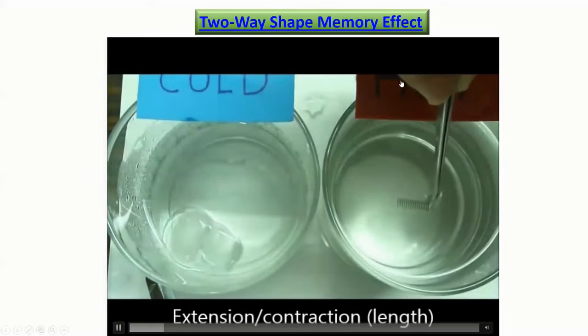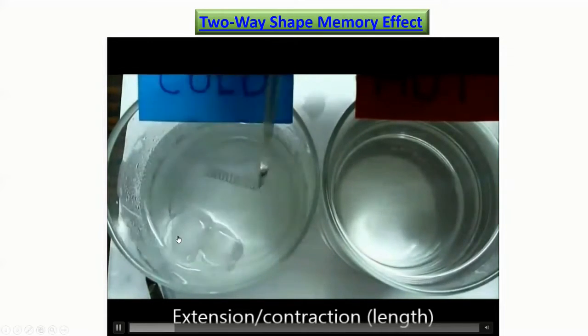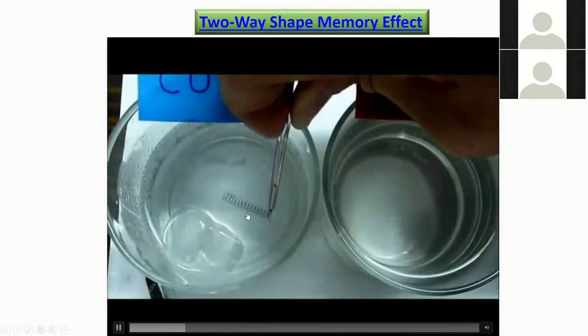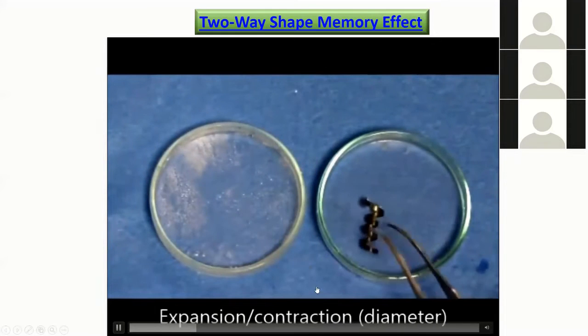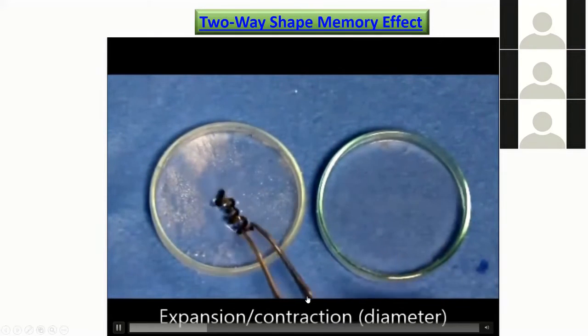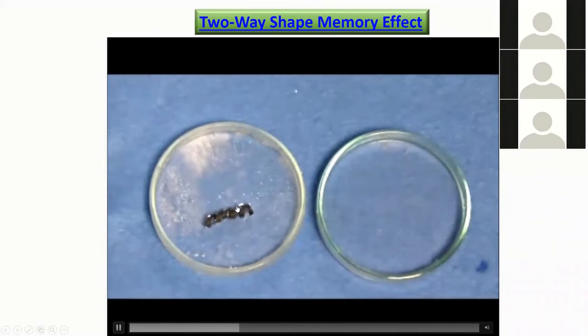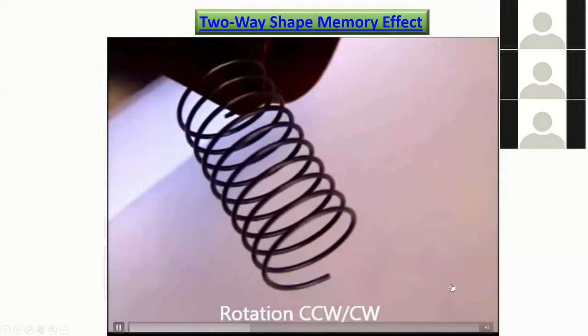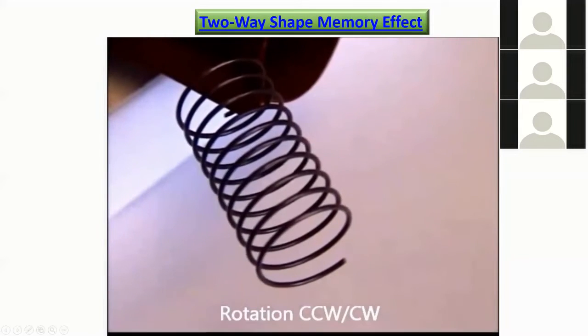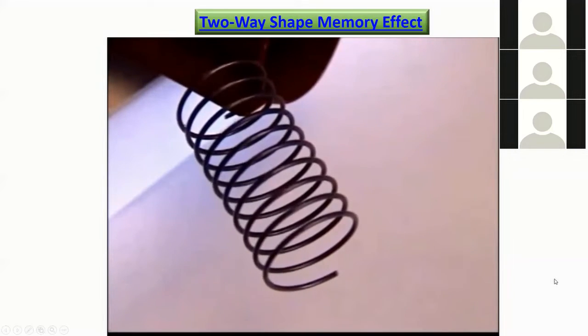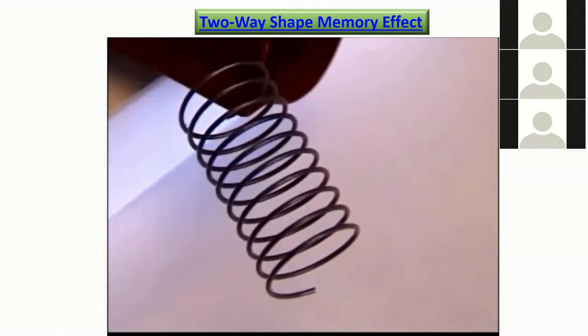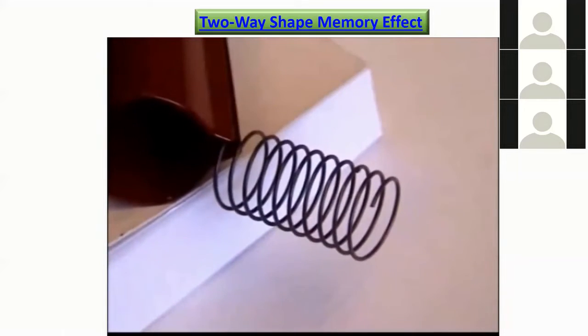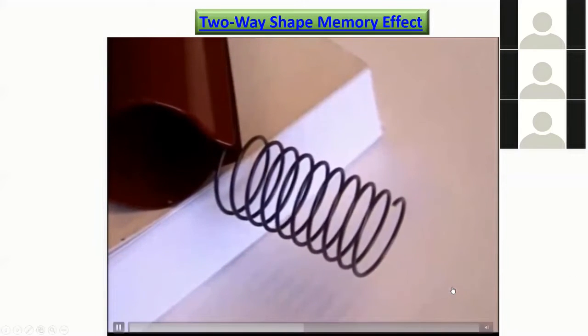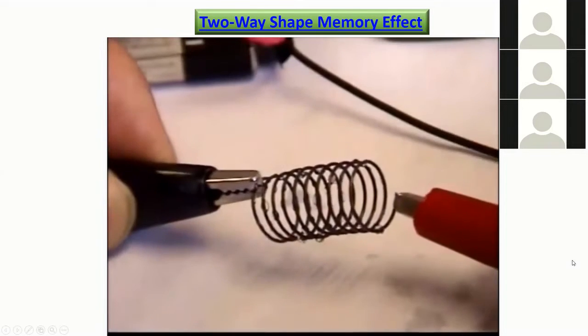So you can see that this is a hot water or hot liquid, and this is a cold liquid, and the spring can have two different shapes. Okay, with the change in the diameter, you can see that this is quite high and this is quite low. So just by changing the media temperature, we can play around with it. And what kind of shape it will achieve in both conditions will depend on the kind of training that we have provided. Okay, we help the alloy to remember its shape in one particular phase and can keep on doing that. So this is rotating on its own just by adding some temperature to it.